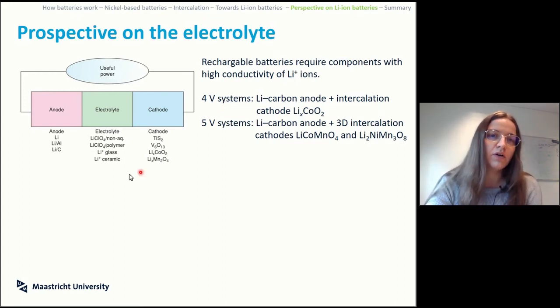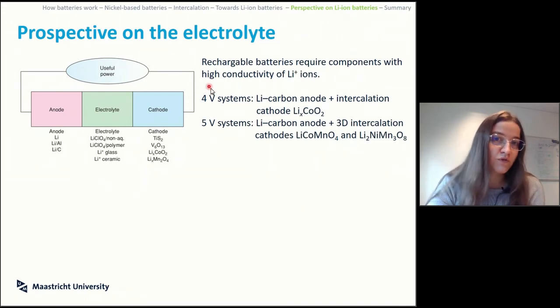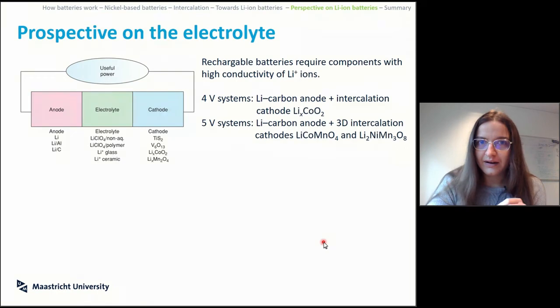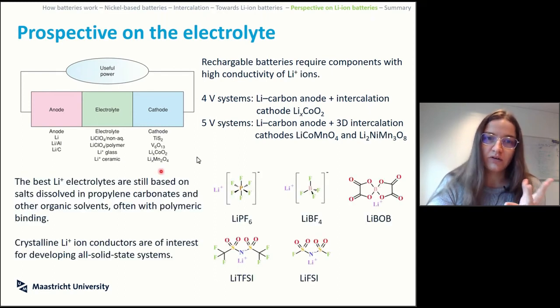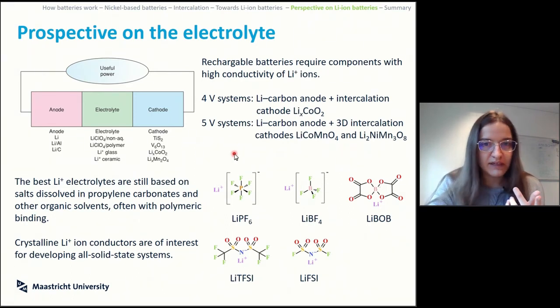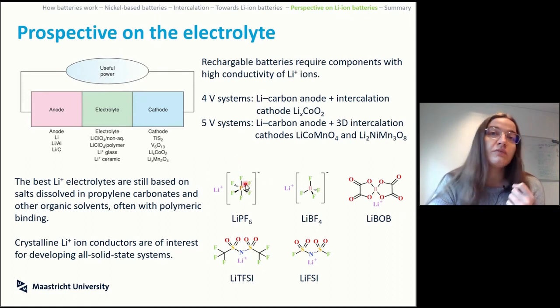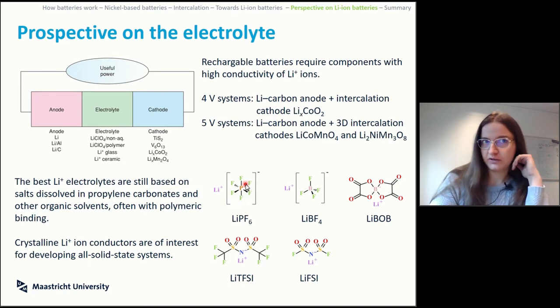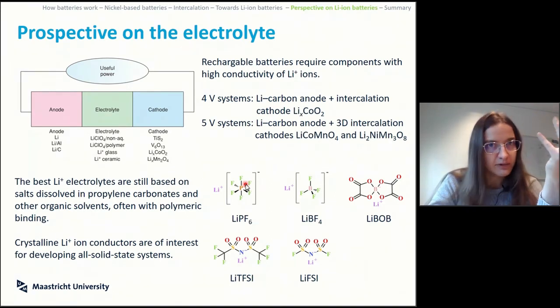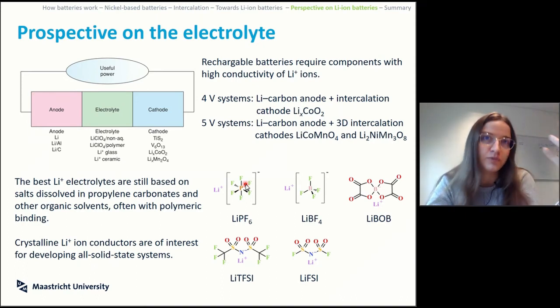The last perspective, which is super tricky, so we're not going to spend a lot of time on it, is the perspective on the electrolyte, because as we discussed, if you want to have a 4 volt or 5 volt system, anode and cathode chemistries are something that also require the electrolyte in between to be matched properly. So at the state of the art, the current electrolytes are still based on lithium salts that are soluble in organic solvents, right? So you have the carbonates that do that trick with the anode, and you put these salts in so that when the lithium plus comes out, it actually has something to coordinate. It could be interesting if we could manage, because this thing still needs some sort of slushy liquids. They're not liquid, but they're still like this sort of goo that you don't want to get out, but it needs volume in your structure, right?